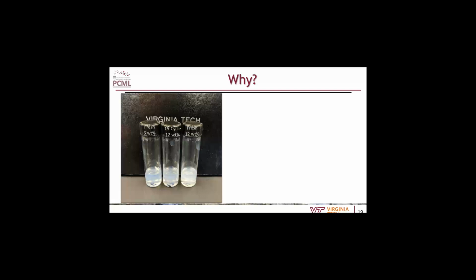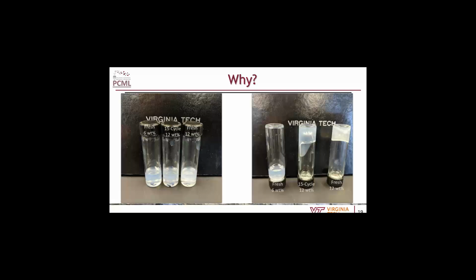The 6 weight percent, they're generally dispersed far enough away from each other that they do not gel, so it will flow around the vial just like water would. So if you flip this over, our 6 weight percent did exactly what we wanted it to. It flipped, fell to the now bottom of the vial, and our 12 weight percent stayed at what is now the top of the vial.